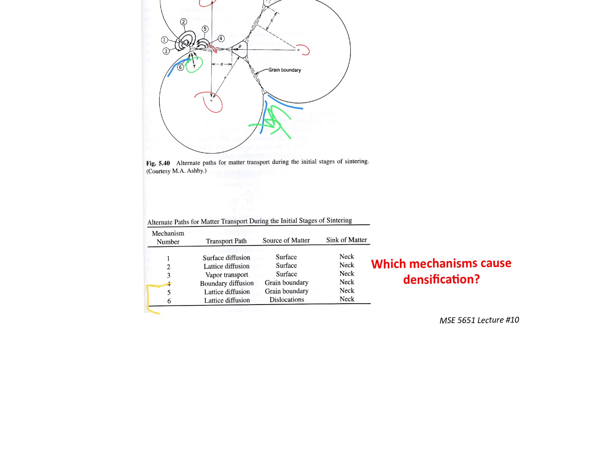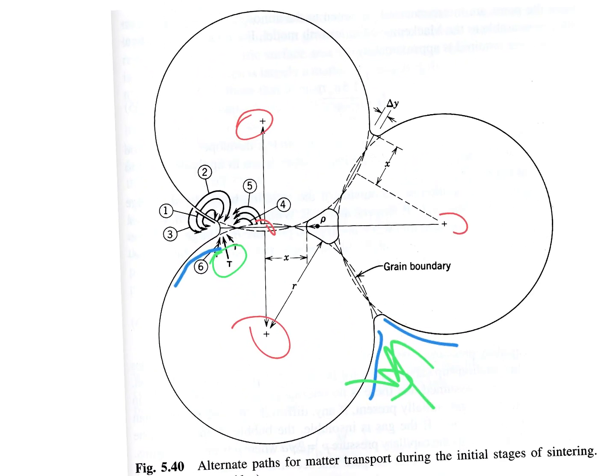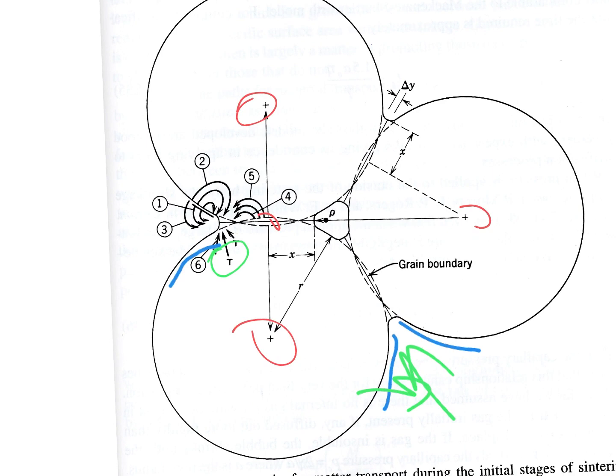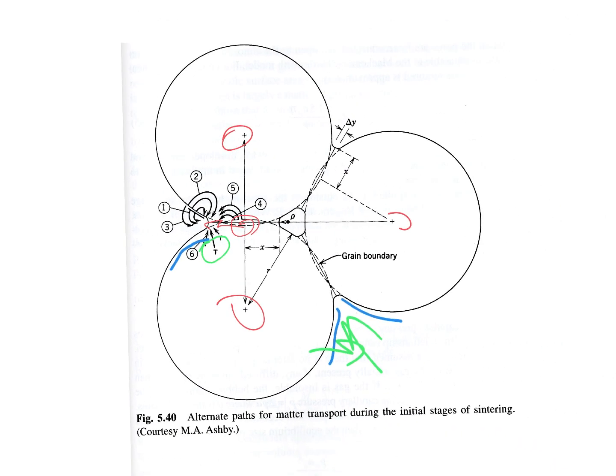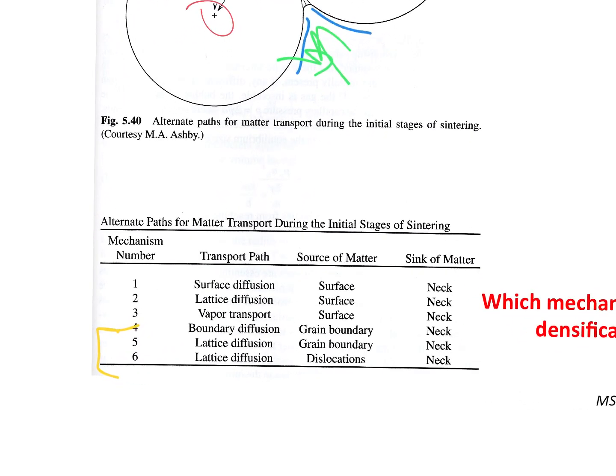And so we're diffusing along the grain boundary, and in doing so, let me go back to this overall picture. If you're diffusing along the grain boundary, let me clean this up a little bit. Diffusing along the grain boundary, which has just been formed, by the way, and you're going to that neck, you're taking atoms away from that space between those crosshairs. And so now these X's, the crosshairs, are getting closer together. You're just shrinking that distance. And so that's an efficient densification rather than inefficient densification. So everyone see that, hopefully? It's just a matter of getting atoms out of that space between those crosshairs.